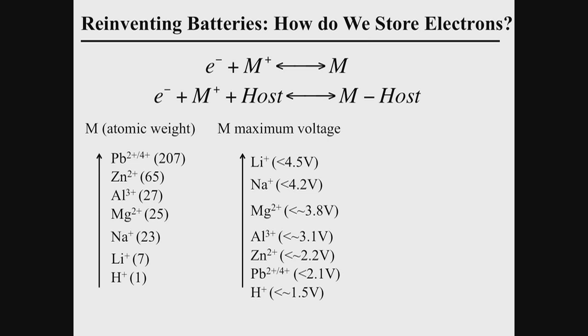However, the second consideration is the voltage. If you take the proton, that's water; if you increase the voltage above roughly 1.5, you start to split water and generate hydrogen gas. So that's not good. The voltage of these proton-based batteries is not high enough. But lithium, the most electropositive element, allows you to go to high voltage, 4.5. Sodium will be a little lower, and this one even lower. So you see the reason lithium is dominating battery technology: it's a reasonably lightweight element, second to proton, but produces the highest voltage, plus it is very lightweight.